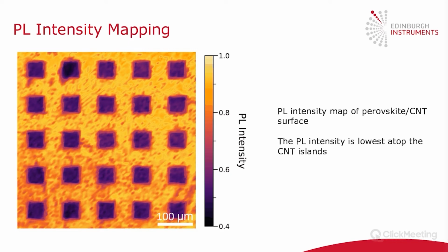Now here is the same substrate, but we've imaged it using confocal photoluminescence. Here the perovskite was excited at 532 nm, which is above its band gap. Electrons are promoted from the valence band to the conduction band, and then they decay back down, releasing light. And so regions with high photoluminescence are shown in the bright yellow here, and regions of low photoluminescence are shown in the dark. And what this is really giving us is a measure of how efficiently electrons and holes are being extracted.